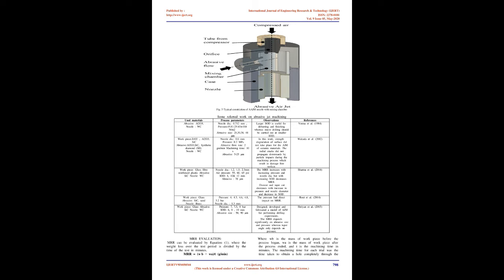the abrasive hardness directly exerts to MRR. Wakuda et al. blasted various ceramic substrates by abrasives with comparable angular shape and size, but different Knoop hardness. As it can be seen from Table 1, in the case of ZrO2 substrate, the erosion rate was almost independent of the abrasive's hardness, as the workpiece hardness was substantially lower than the hardness of any abrasives.